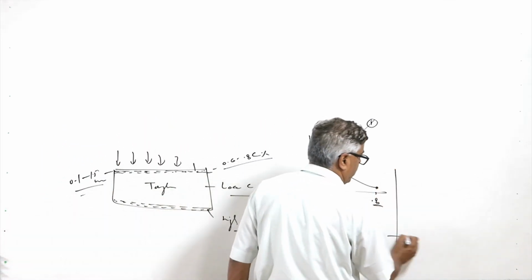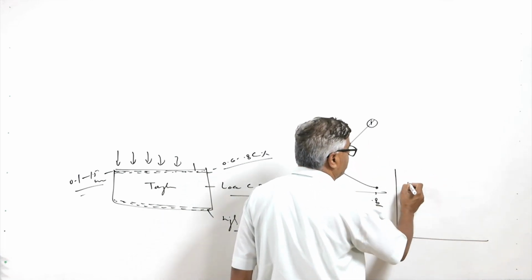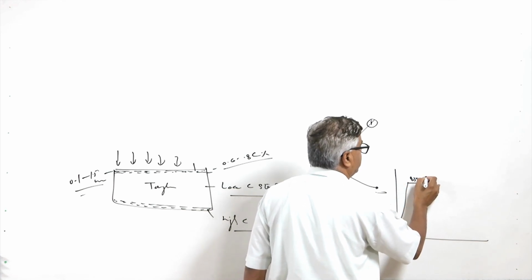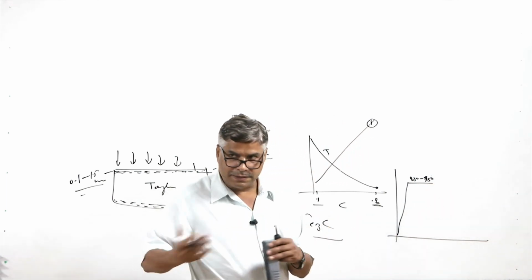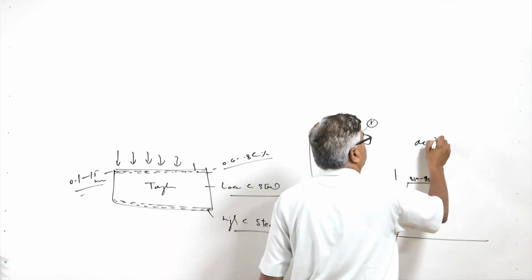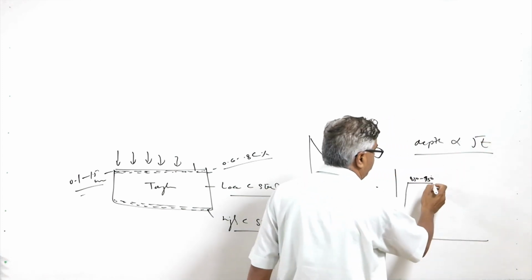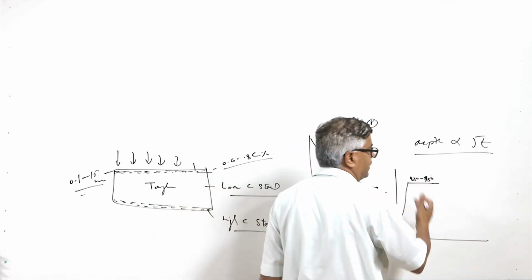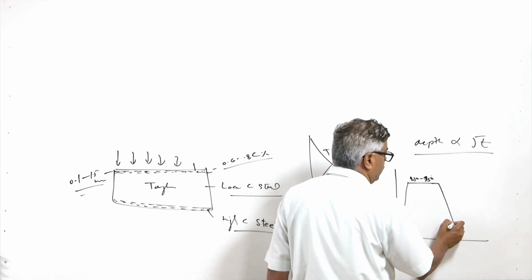That is why the kind of thermal cycle which is used for the carburizing purpose is an increase in temperature up to the range of say 850 to 950 degrees centigrade, and it is held for the time as per the requirement of the depth to be modified, wherein the depth modified or depth carburized is found proportional to the square root of the time. So longer is the time for carburizing, greater will be the depth which will be enriched with the carbon, and then it will be cooled.